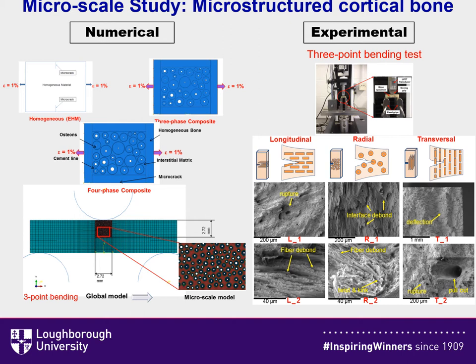These tests demonstrated that depending on the orientation of the crack propagation with regard to the osteons, totally different fracture scenarios can be found in the material, including interfacial debonding, fiber debonding, and others. All these types of mechanisms were found in our numerical multi-scale models, where we were embedding the microstructured domain into the material with effective homogenized properties exposed to the three-point bending as in a real test.